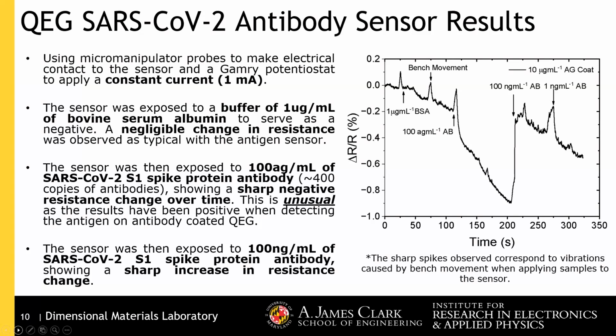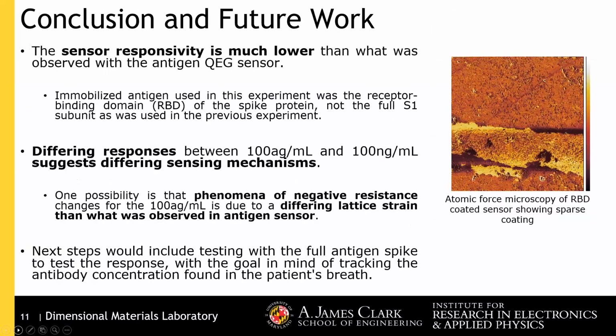That's very unusual. When we do our actual coating and run a sample through it, and things start reacting, we usually get a positive change, so we were kind of confused by that. Eventually, we added 100 attograms per milliliter, and that's when we got that negative change. And then when we changed to 100 nanograms per milliliter, that's when we were back in this positive range. So we've determined that our current sensor responsiveness is much lower than we initially expected and hoped for. But part of science is making mistakes and learning from them. So this is a very ongoing process. It's more about furthering the capabilities rather than going for a specific expected result at the end. And the different biosensors introduce different sensing mechanisms.